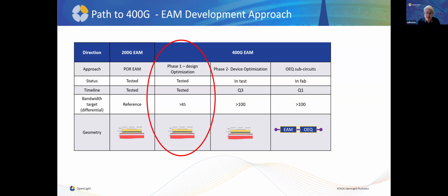To go much beyond 85, and this is what we're actually testing in the lab today, you need to do a device optimization, and that's primarily a change in the indium phosphide material. As you shrink the device size, some of the other optical parameters tend to suffer. You lose a little bit on extinction ratio, for instance. You need to maintain the insertion loss and drive swing as well. So by changing the quantum well structure is how you go from 85 gigahertz bandwidth up to 100 gigahertz, whilst maintaining enough extinction ratio and other parameters to be able to support PAM4 at these data rates.